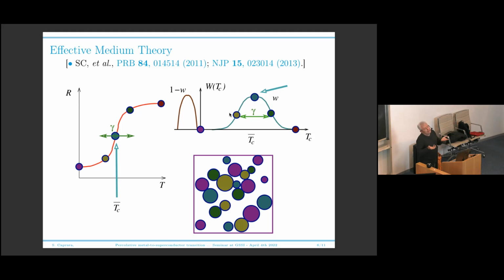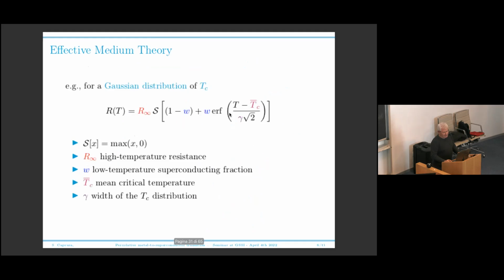Maybe you don't know the distribution because the data are so noisy that it's very difficult to tell from the data whether this distribution is a Gaussian or maybe a Lorentzian. I will come back to this point later on, where anyway you can say something. But you can extract nonetheless some significant parameters. For instance, if you have a Gaussian distribution of critical temperature, you have an exact analytical solution within the effective medium theory. This is just the solution.